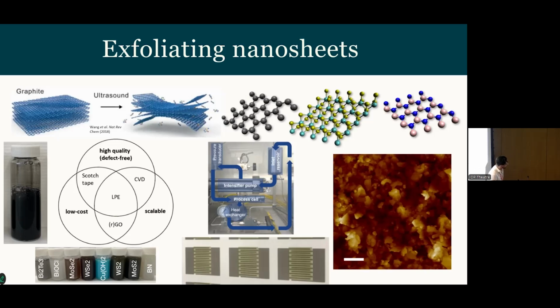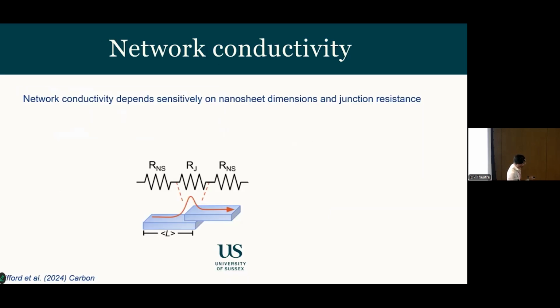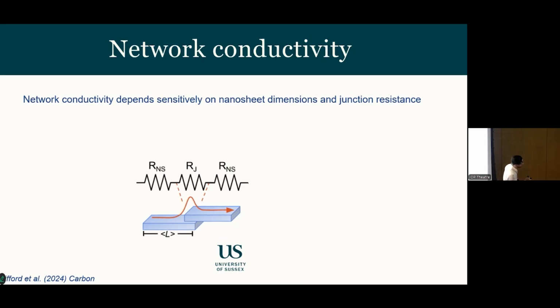So now that we've got lots of these materials, we can look at how the network conductivity, so the conductivity of a macroscopic film of these materials, depends on the nanosheet properties. Of course, as we make the nanosheets smaller, the resistance of the individual nanosheets goes down, or the length goes down, but the thickness goes down as well. But maybe most importantly, the junction resistance, which dominates the transport in these films, we would expect that also to increase, because we're making the overlap area between the sheets smaller, unless we're also changing something else about the system.